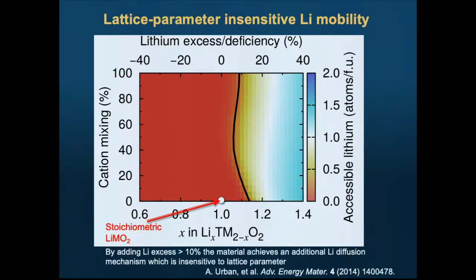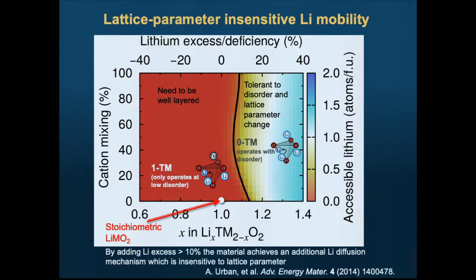This is the design map, essentially. This is the lithium excess. This is the cation mixing. So here you are ordered, here you are disordered. Essentially, when you cross this line, this is the percolation line, you can actually operate with cation disorder, right? And again, you see now why that's important. We can operate with cation disorder. That means we can use any chemistry in the periodic table because we don't care if the ions start to migrate out of their ordered configuration.